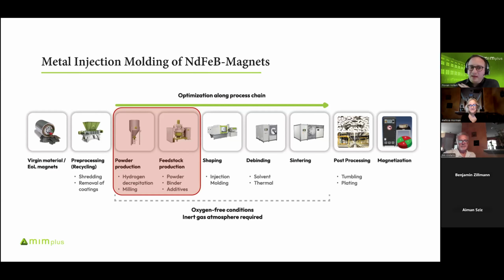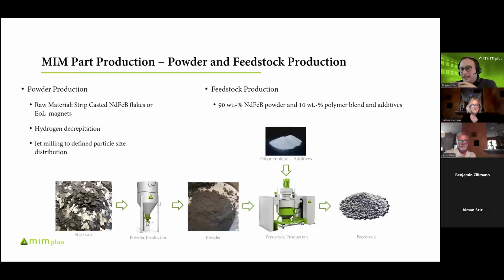Now, I want to go a little bit more into detail on the powder production and the feedstock production. Basically, the powder production is the same as for a press and sintered magnet. We are using our raw material or end-of-life magnets. You see our raw material, strip casting flakes. We put them into a reactor that is filled with hydrogen. The hydrogen diffuses into the material, which goes along with a volume expansion, and then the material falls apart, and you get a relatively coarse granulate.